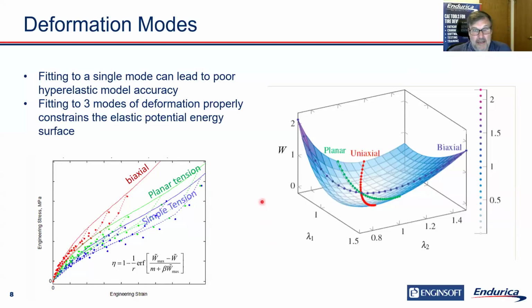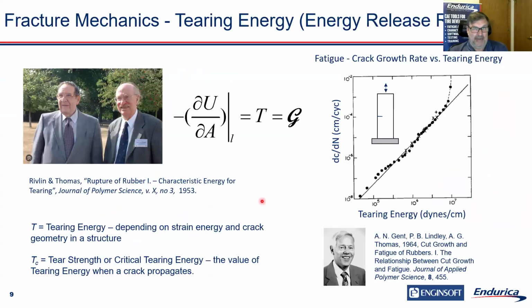Thanks, Kurt, for that. And now we're going to move on to fracture mechanics. Fracture mechanics started its birth in the 1920s with a man called Alan Griffith, who came up with the concept of energy release rate, sometimes denoted by a script G. That concept was extended to rubbers by Alan Thomas and Ronald Rivlin, with their paper published in 1953, where they said the tearing energy in a structure is like the change in the strain energy divided by the change in crack area.